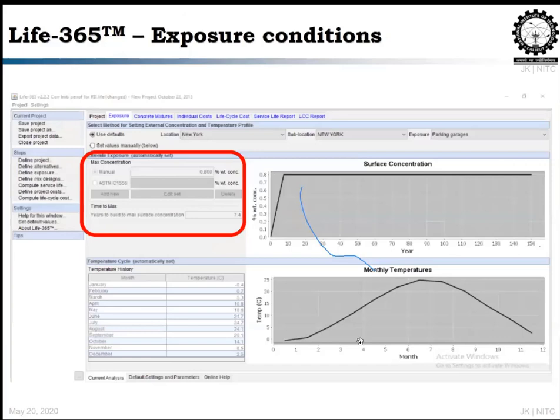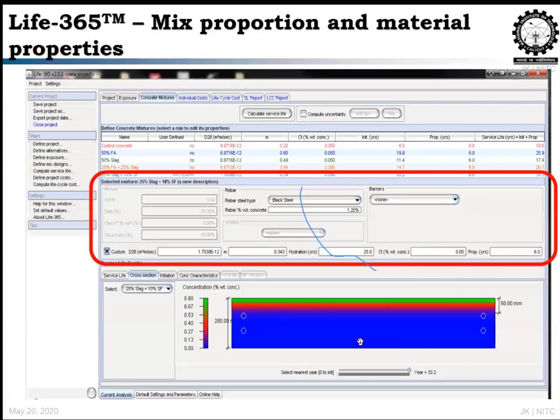You have only a few places which are preset, but you can give your own custom temperature, humidity, and your own aggressive environment. And this is the main component where you can define your water cement ratio. For example, in the red box, it shows a water cement ratio of 0.2, and the slag which is used as 25%.